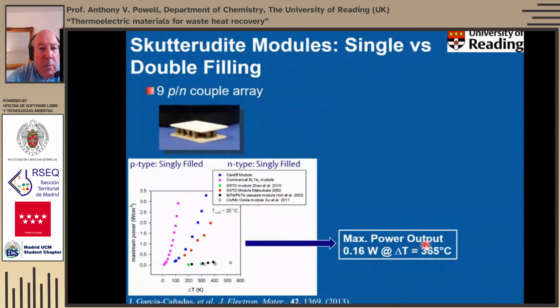So we then started thinking about module construction. We'd previously collaborated with Gao Min at the University of Cardiff on single-filled skutterudites, where the N and P type were both single-filled. So this is one of the modules that they produced from our materials. This is a 9-couple array. And what's referred to in this diagram as the Cardiff module gives about 3.5 watts per cubic centimeter. If we compare that with the one in pink here, which is a commercial bismuth telluride module, what we're really getting is bismuth telluride performance, but now at somewhat higher temperatures. And we get a maximum power output of about 0.16 watts from this module at 365 degrees C.